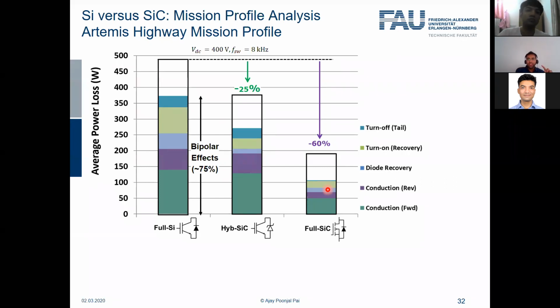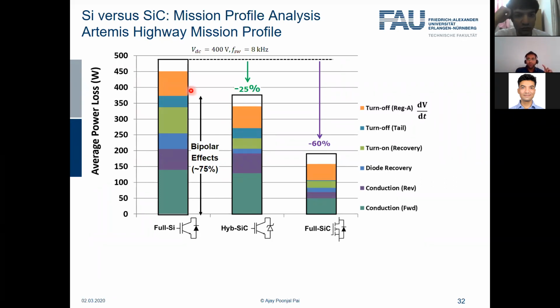Now comes the remaining part. If you remember in the turn off waveform I showed, there was a region A, region A, B, and C. Yes, blue curve. The region A was due to the DVDT, or the slew rate of the voltage. How fast is the voltage going down? And here, if you see, this is more or less the same for all the three devices, which means I have taken care to see that the devices are switching at similar speeds as far as the DVDT is concerned. Why did I do this?